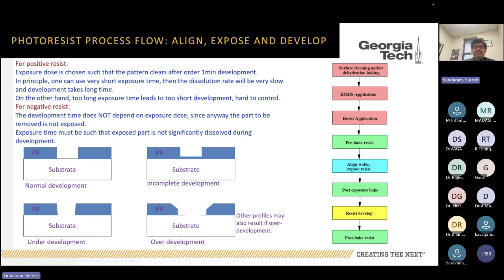So for positive resist and negative resist, as I told you, depending on what kind of chemistry we are using, you will have something like these. For normal development, we will have substrate that is exposed to air without any photoresist. This is incomplete development. You can see some photoresist on top of the substrate. If you are etching more substrate, this is under development, and if you are over developing, you can etch the wafers also, depending on what you are using. Normally gallium nitride wafers are chemically very robust, so you will not be able to etch gallium nitride using non-metal chemicals. If you want to etch gallium nitride, you have to use potassium hydroxide, but that's not compatible with photoresist also.